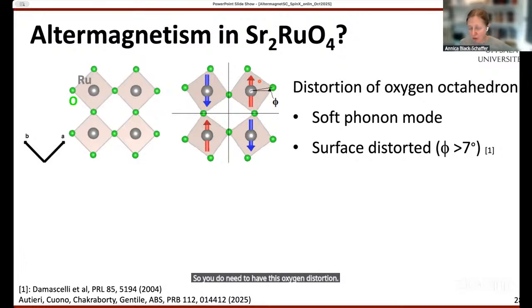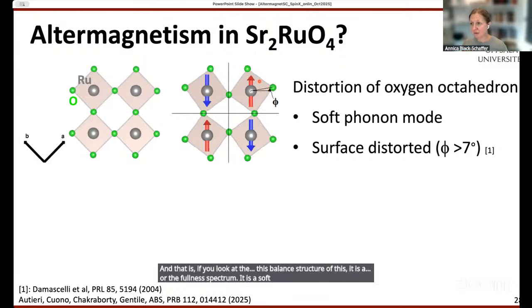And if you look at the phonon spectrum of this, it is a soft phonon mode. It's not an imaginary phonon, but it is soft, so it's easy to happen. And also the surface of strontium ruthenate is known to have a rather large distortion, up to 7 degrees actually, of this particular distortion. So nonetheless, at the very least, this will happen on the surface of this material.